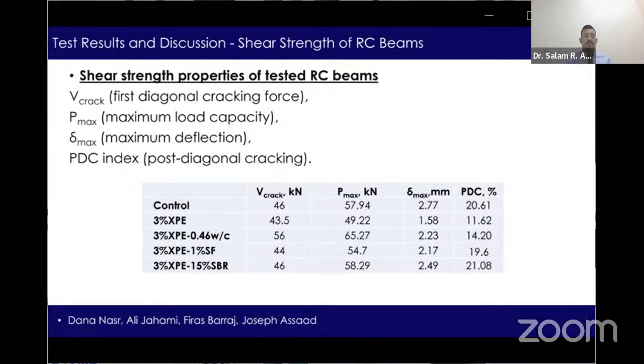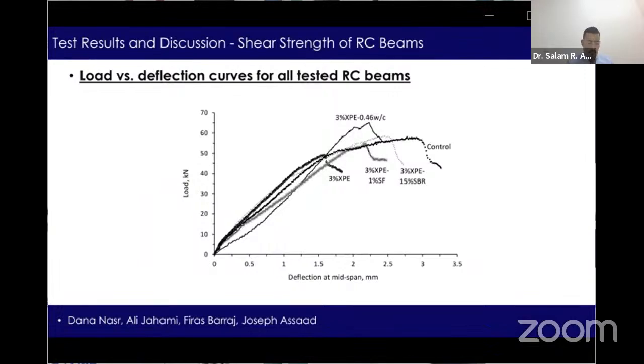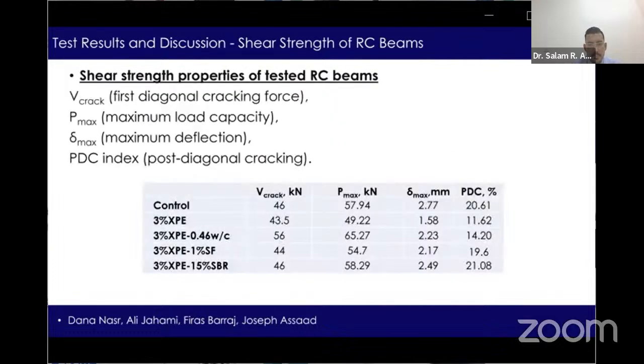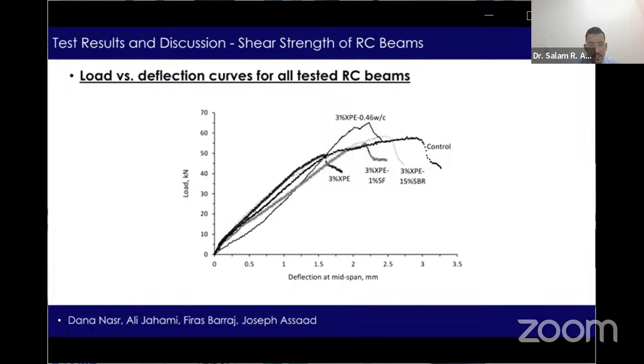On the other hand, when 3% XPE was added, we can see that this addition of XPE greatly reduced the shear strength properties, resulting in a drop in Pmax that reached 49.22 kilonewton and a drop in the corresponding delta max to 1.58 millimeters. This drop may be due to many reasons. One reason may be the reduced concrete density and strength, which both can weaken the beam's resistance to applied loads. Another reason may be the poor interfacial adhesion between XPE particles and the cement matrix, which results in decreased shear transfer along the diagonal crack surface and leads to sudden beam failure.